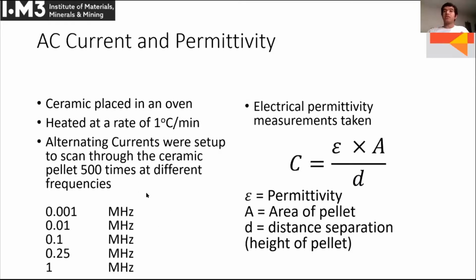These scan through the ceramic pellet 500 times at different frequencies. Because we had different samples, these differed in geometry, so the sizes of the samples would affect how much charge they can store. So in order to effectively compare them and account for the size difference, we multiply the permittivity by this geometrical feature of area over distance, and that gives us the capacitance, which is a better comparison quantity.